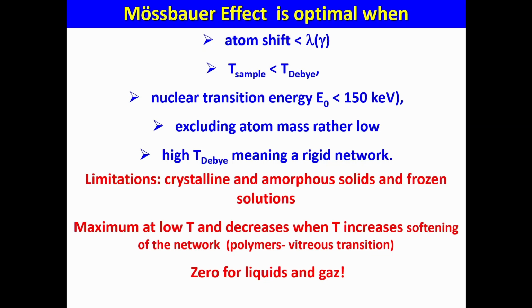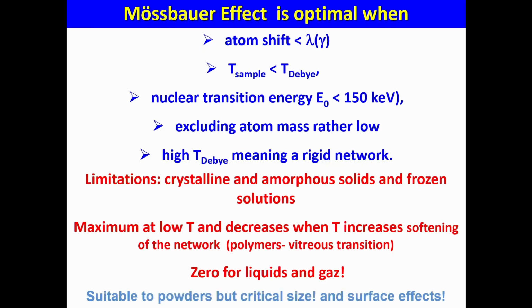As I mentioned, we have some constraints. It is not possible to observe on gases and liquids. You need solid state. If you have a liquid, there is a possibility to freeze it down. And the effect is much more important at low temperature than at high temperature. That is why it is possible to follow the F factor versus temperature, which can be established from the surface of the absorption area, or the surfaces of absorption areas if there are different components. I have also mentioned that in the case of nanostructures, take care of the surface effect.